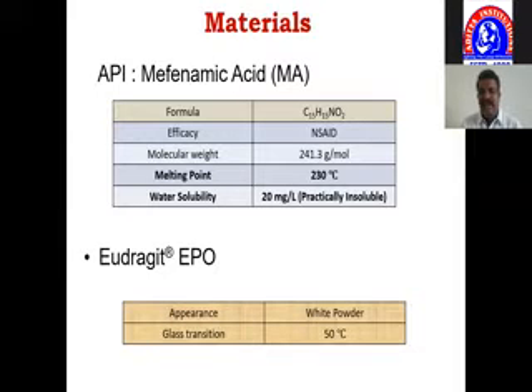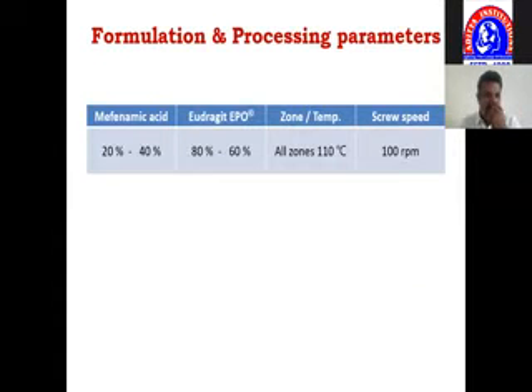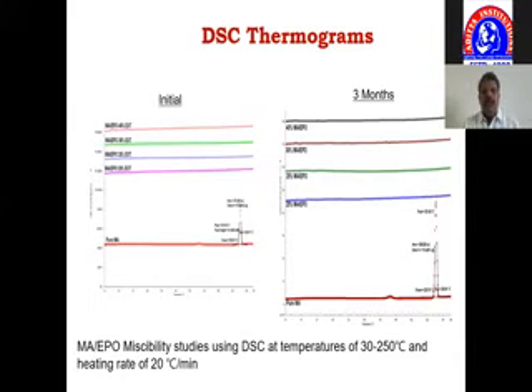The melting point of the drug was 230 degrees centigrade. So we have selected Eudragit EPO. The glass transition temperature of Eudragit EPO is 50 degrees centigrade. So now the formulation conditions: we have used mefenamic acid from 20% to 40%, and the temperature for processing was 110 degrees centigrade. Now here again, when we ran the process with Eudragit EPO and mefenamic acid at 40%, 30%, 25% and 20%, all of them showed no drug melting point, as you see in the pure mefenamic acid, MA, at the bottom.